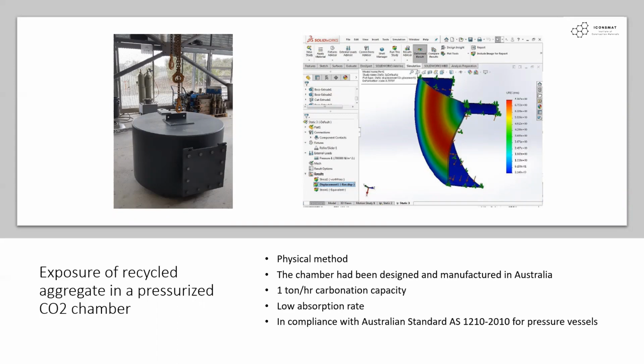Before 2018 in Sydney, there was only a chamber with 50 kilogram carbonation capacity. You can actually find this behind this picture, that cubic pressure vessel is that 50 kilogram pressure vessel. Our research team had made an effort to design and manufacture and upscale the chamber with the capacity of 1 ton carbonation per hour. The picture on the left is the picture of the new chamber, and the picture on the right is our design for deformation of the steel shell, which is limited to 6 millimeter on each side based on the recommendation of AS 1210 for pressure vessels. The chamber can easily take up to 700 kilopascal of gas pressure inside.